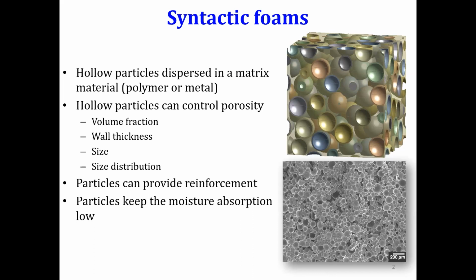And what presently we are doing pertaining to these materials in the 3D printing regime, I'll present as part of this. So my group basically works on syntactic foams, wherein we introduce hollow micro balloons in the resin. And these resins can be thermoplastic, thermoset, metal, ceramics, and so on and so forth. The advantage we get here is that we can have a property variation based on the micro balloon volume fraction, which is generally talked about in composites. But in addition to that, for the same volume fraction, if we change the wall thickness of each of the micro balloons, we have different density particles and different properties altogether.